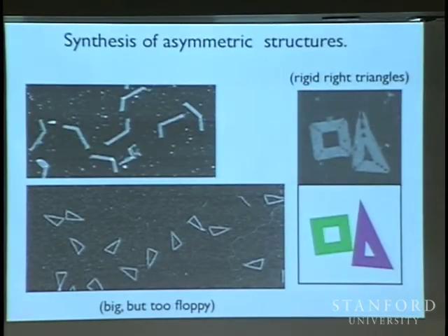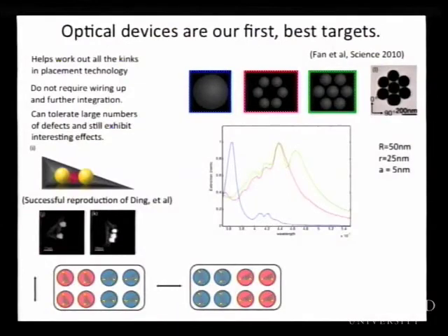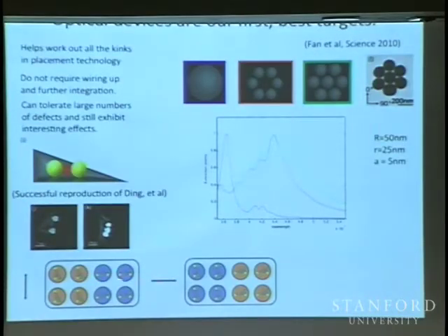Another interesting device direction, I think, is if we take one of those triangles that I showed you, like one of these asymmetric right triangles, we hope to put little metal dipoles on these. This little pair of particles has a very different resonance than a single particle, and its resonance is polarization dependent. So what I've tried to draw down here is that there's a resonant mode parallel to the long axis of the particles and one perpendicular to it. If you excite with light polarized in this direction, you have to excite with red light to get good scattering, or in this direction, with blue light.